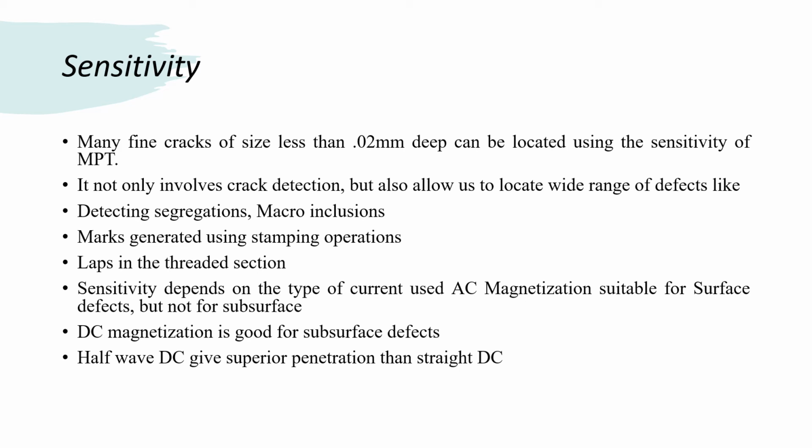But in general, a surface discontinuity whose depth is at least five times its opening at the surface will be detected. Exceedingly wide cracks will not produce a particle pattern if the surface opening is too wide for the particles to bridge.